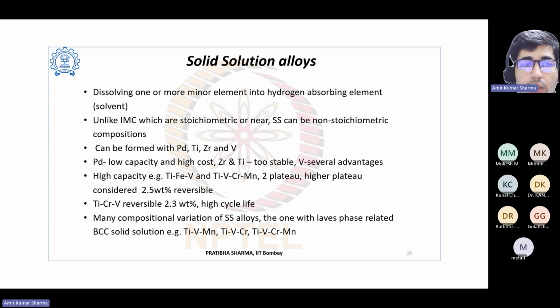Then we have solid solution alloys. In this, one or more minor elements are dissolved into a hydrogen absorbing element, called the solvent. Unlike IMC, which are stoichiometric or near stoichiometric, solid solution (SS) can be of non-stoichiometric composition. It can be formed with Pd, Ti, Zr, and V. Pd has low capacity and high cost; Zr and Ti are too stable. V has several advantages: high capacity, like Ti-Fe-V and these. There are two plateaus, and the higher plateau is considered 2.5 wt% capacity and reversible.